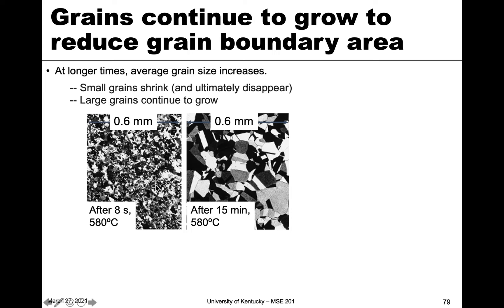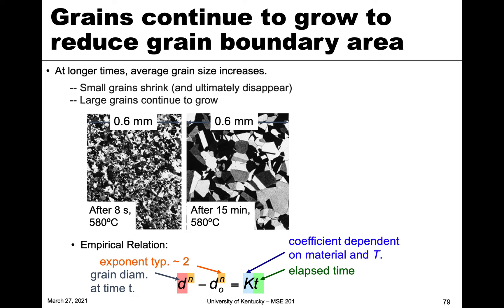After recrystallization — which we define as right when all of the prior grains are consumed — from that point on is known as grain growth. Here you can see at eight seconds for this experiment, that's what happened. And then after 15 minutes, those grains have grown. Some of them are larger, some basically disappear as the larger ones continue to grow. The driving force here is the reduction in grain boundary area.